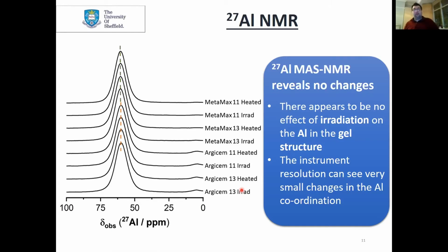If we compare these two aluminium-27 peaks, highlighted with the orange and green lines, fundamentally nothing has changed. The green line at the top and the orange line at the bottom represent the Metamax and the Argicem systems, the rotary and flash calcined systems respectively, and there is a slight difference in peak position. This shows the machine is capable of seeing small changes in the crystal structure of the material, but it hasn't seen any change based on irradiation compared to the heating of these samples.